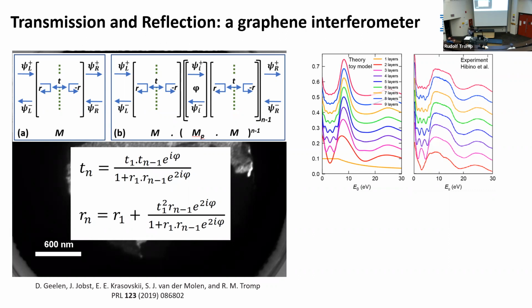Amazingly, if you use this formalism and calculate what these curves look like, they look like this. This is experiment, this is theory. Right? The only thing we've done is that as the energy increases here, you can see that for the 1 layer case, the reflection is constant up to the plasma energy and then slowly decays, right? And that way we can reproduce these experimental results with this very simple classical optical theory. So if we put an arrow here where the reflectivity is very small, this is an anti-reflective coating for electrons.